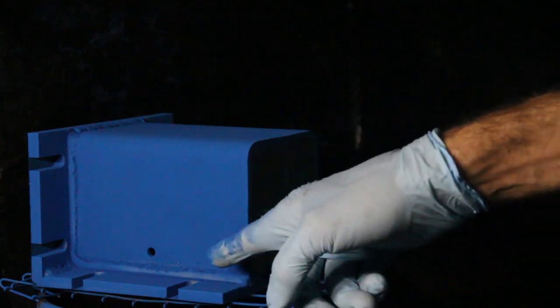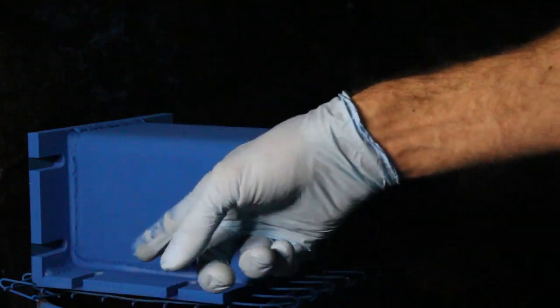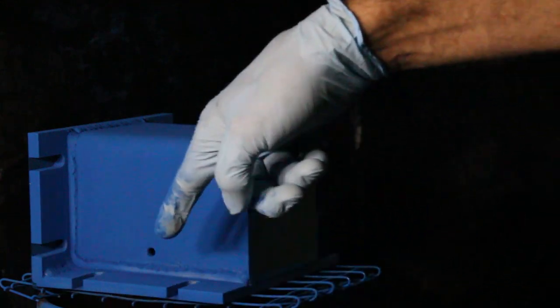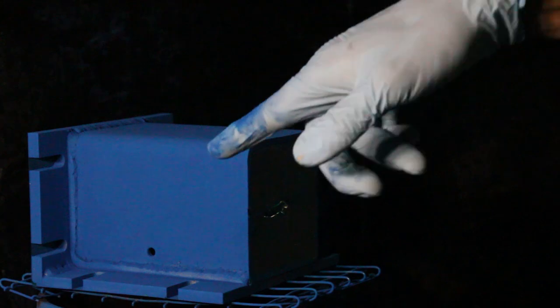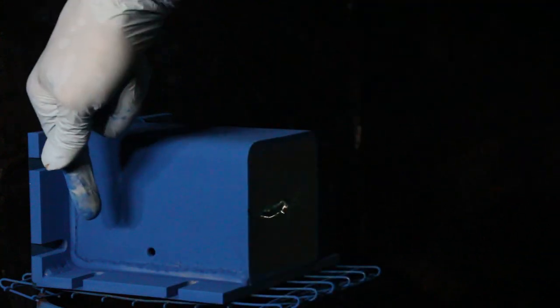That looks pretty good. Down in these corners it tends not to coat as well—there's somewhat of a Faraday cage effect where the electrostatic charge is effectively weaker in those gaps—but I'm not too worried about those areas; they're going to get abraded by fasteners anyway.